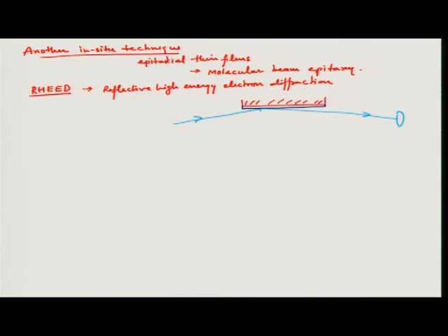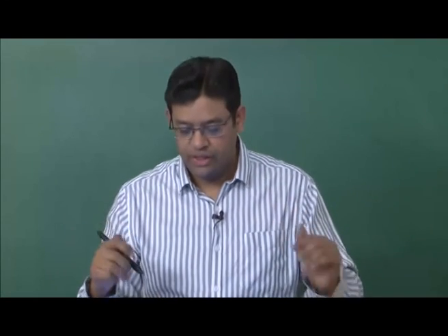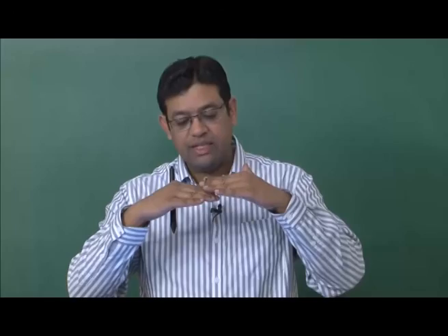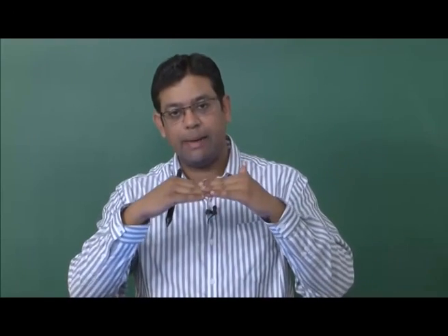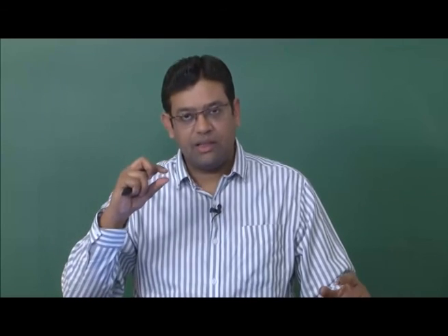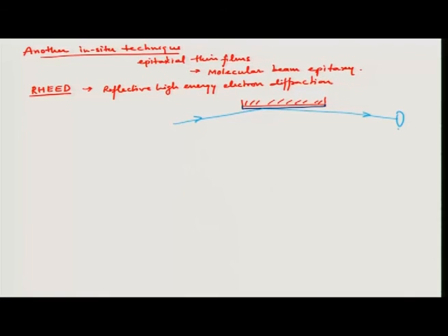And with this you can see the formation of a monolayer, one single layer coverage, okay, and it is very sensitive. So, if the monolayer coverage is not complete, there will be a difference at different places in the step height, which would be one atomic layer thick, and then you will see the oscillation in the diffraction pattern on the detector. Okay. And once this monolayer is complete, then you will see that those oscillations stop.